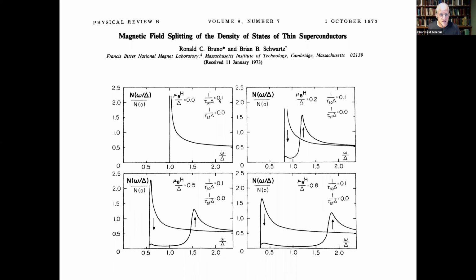Here is a zero magnetic field, effectively small spin orbit, small spin flip scattering, and you have a density of states. Now, if you turn on a magnetic field, turning up the magnetic field, you split the density of states. Let's keep spin orbit and spin flip small so that you see this splitting of the density of states. So far, so good. So when they talk about the gap in this case, in that previous study, they were talking about the order parameter magnitude. That is not the same as, let's call it, the gap in the density of states. That's a different quantity, which goes by the letter omega here.